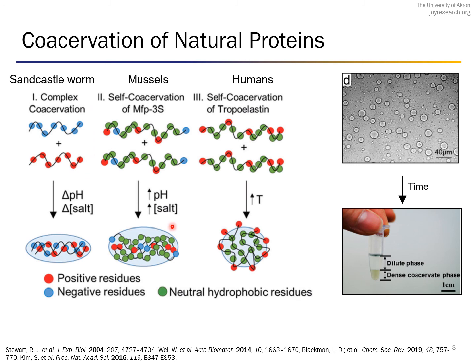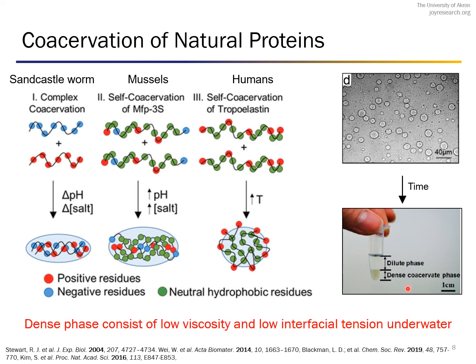At the same time, humans also interestingly have this phenomenon in several organelles. One such is tropoelastin. This tropoelastin is a protein which undergoes such a droplet to dense phase transition with temperature. This tropoelastin has an LCST temperature in water, which helps it to form these droplets and then the dense phase. And the unique properties of this dense phase are a low viscosity and ultra low interfacial tension under water conditions.